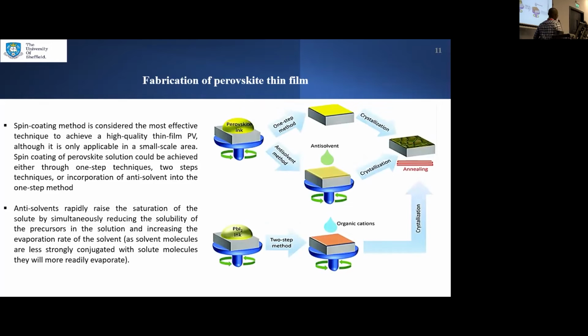Basically, this can be done either by introducing anti-solvent or by directly coating, fabricating your perovskite material. So by directly spin coating our perovskite on a glass substrate and then annealing for some time to create a perovskite crystal surface. Or we can also introduce an anti-solvent during spin coating. Here you can see we have anti-solvent to produce a perovskite surface. And then finally, we can just go through using two methods.